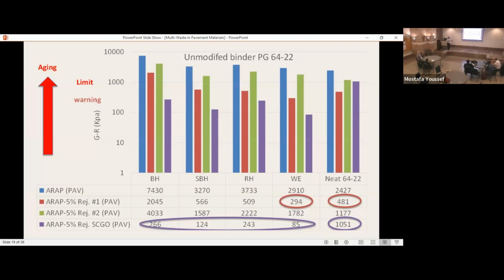So if you compare the purple color, which represents the oil that we generated, after the application of the fly ash, you will see a significant drop in the value of the Glover-Rowe parameter. With the other additives, you see a drop in the effect on the binder, but as we incorporate the ashes in them, we're getting some mixed results, or I would say a little bit of increase, no change. So the effect of the ash on the rejuvenators is not as clearly observed as with this type of oil.